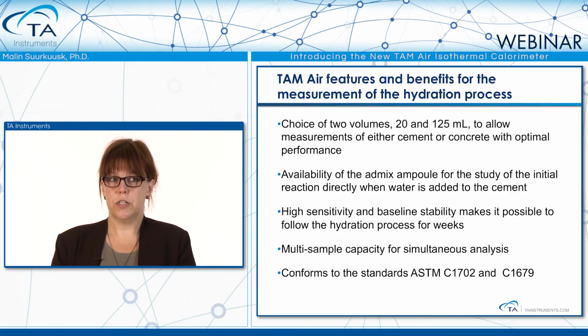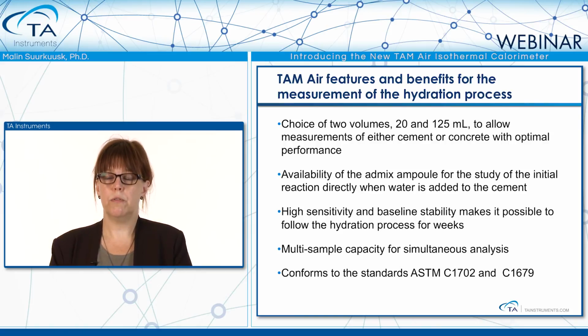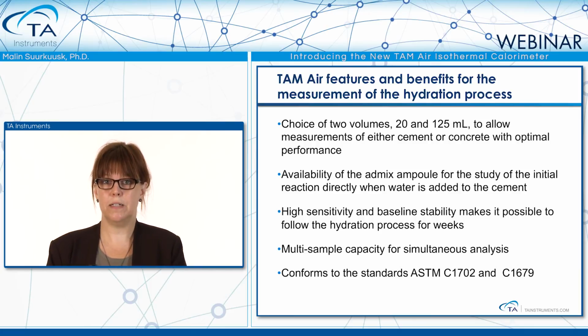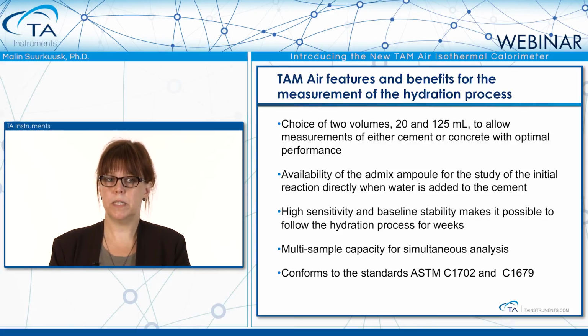So to summarize some features which are beneficial when you use TAM Air for the measurement of the cement hydration process, you have a choice of 2 volumes, 20 or 125 milliliter, that will allow either cement and concrete samples to be measured with optimal performance. We have the availability of the admix ampoules to allow the measurement of the initial reaction in the cement when water is added directly inside the calorimeter. It has a high sensitivity and baseline stability, which makes it possible to follow the hydration process for weeks. And it has multi-sample capacity for simultaneous analysis, and it conforms to the ASTM standards C1702 and C1679.